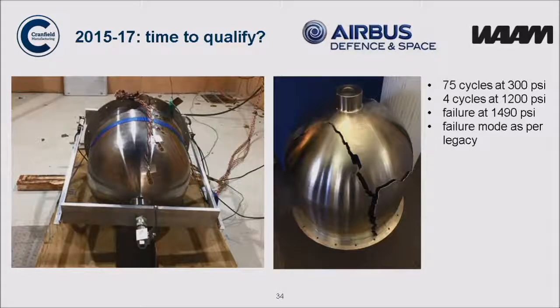And this is the part after it's failed. We did 75 cycles at 300 psi, which is the operating pressure. We then did 4 cycles at 1200 psi to test that out, and then we tested it to failure, and the failure mode was exactly as per the forging. So it performed identically to the forging. We get performance that's identical.